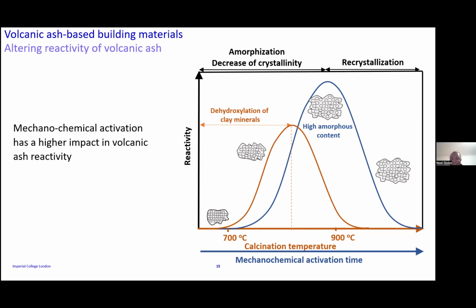And for any material to be suitable for using either as SCM or as a raw material to make geopolymer, it needs to have a high amount of amorphous phase content. Amorphous phase means the crystals that have been destroyed or dismantled. So the material is easy to handle by any chemical. So by doing the mechanochemical activation of the volcanic ash, we obtain very interesting results, and I will be showing some of those results with you in my next coming slide.